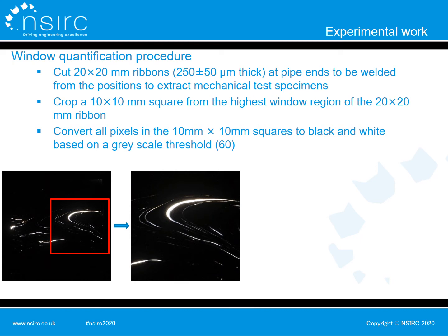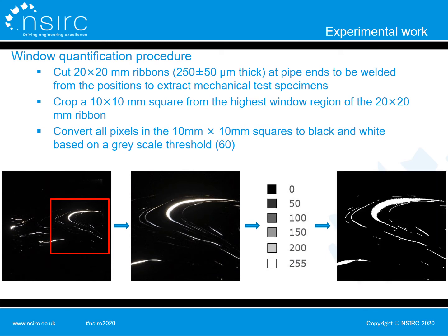After that, all pixels in the 10 by 10 mm square were converted to black and white pixels based on a grayscale threshold, which is 60. For example, here is a scale bar of the grayscale. The grayscale of pure white is 255, and that of pure black is 0. If a pixel's grayscale is higher than 60, then it will be converted to a pure white pixel, otherwise it will be converted to a pure black pixel. Finally, the percentage of all the white pixels was calculated as window percentage.